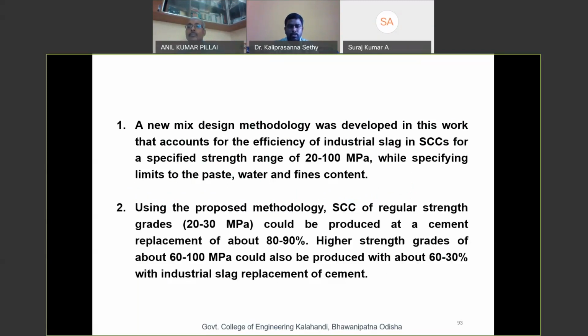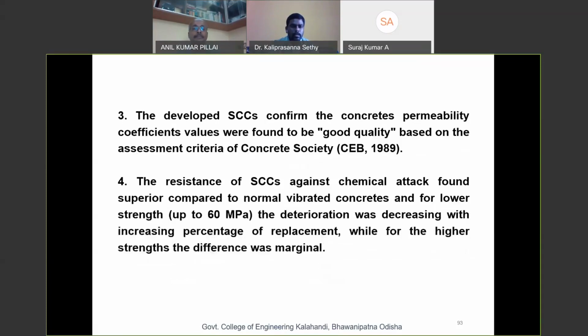Using the proposed methodology, self-compacting concrete of regular strength, that is 20 to 30 MPa, which we use in regular manner, could be produced at a cement replacement of about 80 to 90%, and higher strength grades of about 60 to 100 MPa could also be produced with about 60 to 30% industrial slag replacement of cement. The developed self-compacting concretes' permeability coefficient values were found to be very good based upon the assessment criteria provided by the Concrete Society, and the resistance of self-compacting concrete against chemical attack was found superior compared to normal vibrated concretes.